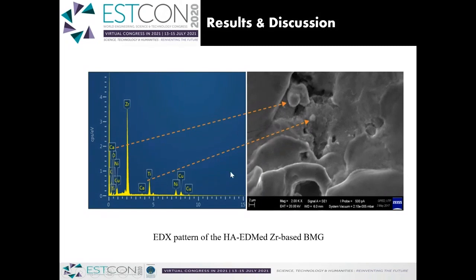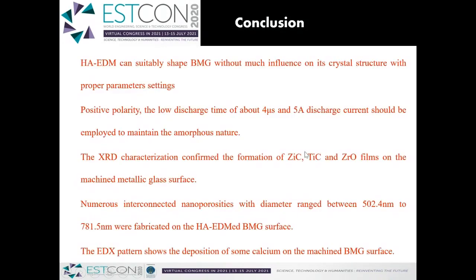This confirms that the EDM process is a good process for depositing HA, or for coating the surface of bulk metallic glasses. In conclusion, we can say that HAEDM can suitably be used to shape BMG without much influence on its crystal structure when proper parameter settings are utilized. And also, when 4 microseconds and 5 ampere discharge time and discharge current are utilized, then the amorphous nature is much more maintained.